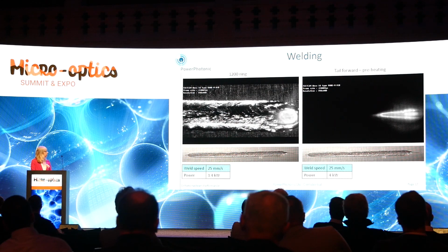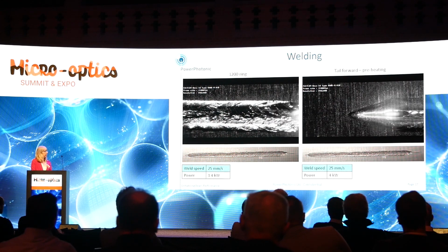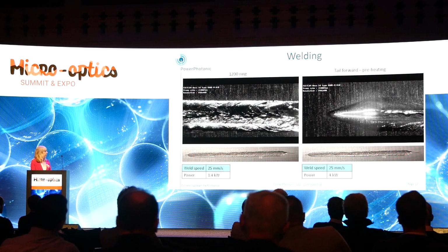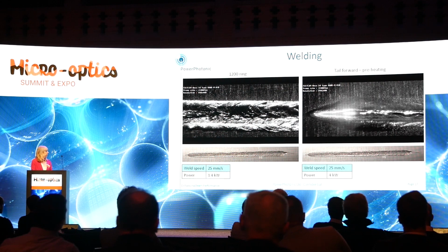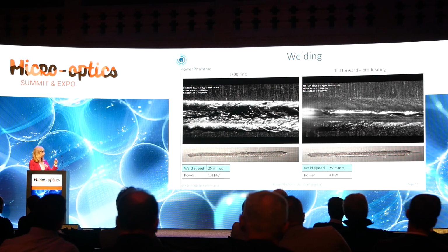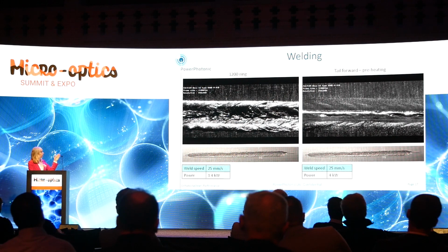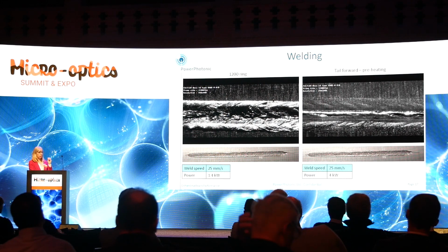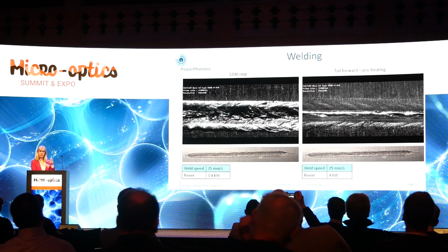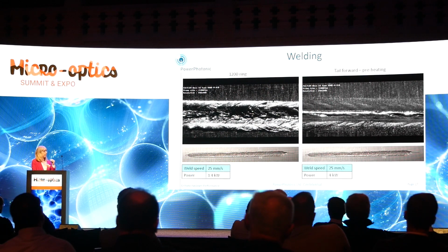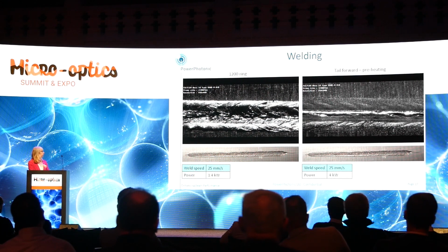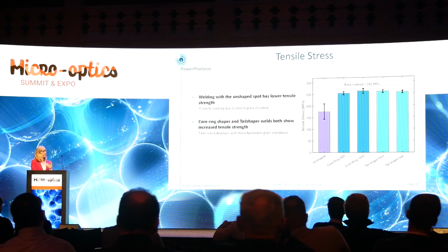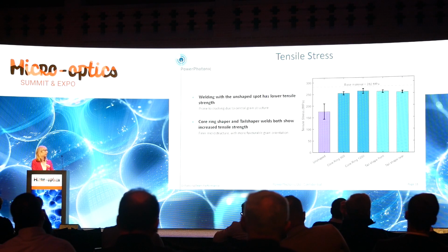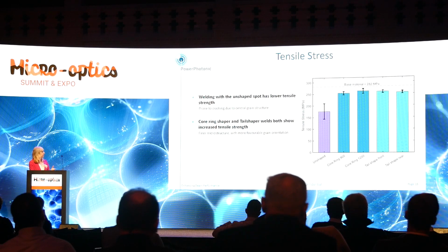And then the tail shaper, which we like to show, is a nice smooth weld. You can see the grain direction. And again, at the bottom, there were no lumps and bumps and air pockets. I haven't got the slides here, but there was some testing done to show that both of these welds caused a lot less cracking, there weren't as many holes, it was much less porous. So the best way to show that for me today was to show you the tensile strength. Without those holes and cracks, the tensile strength was improved.